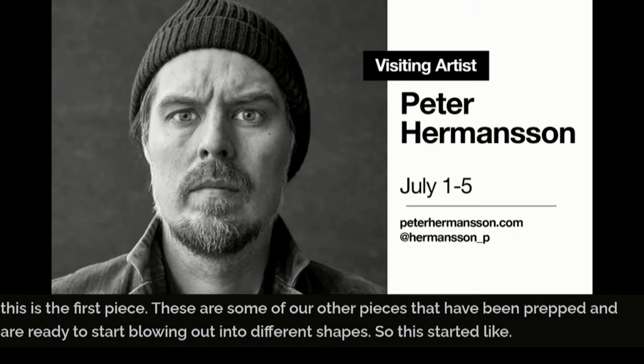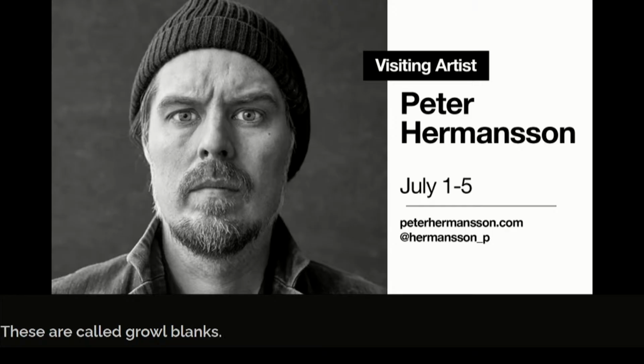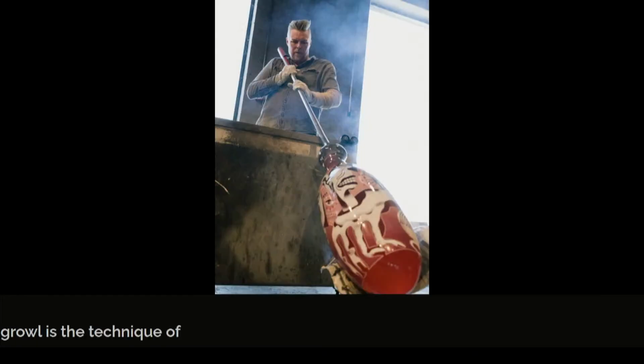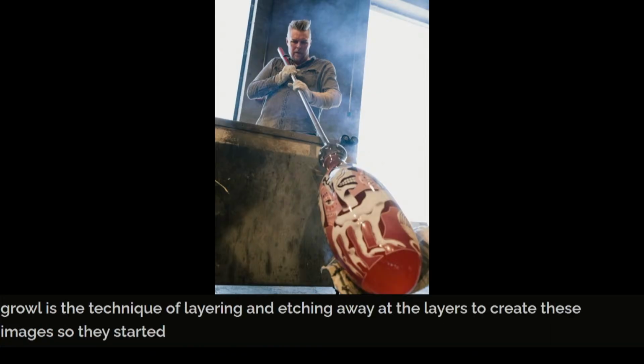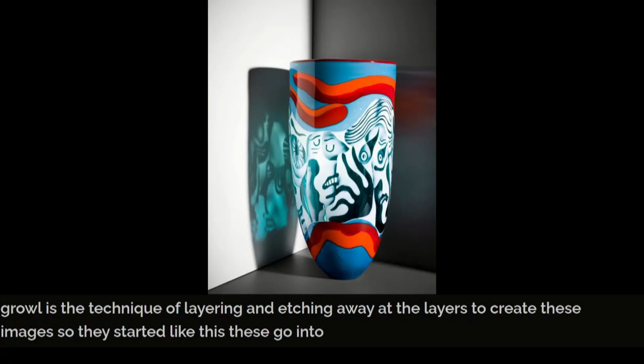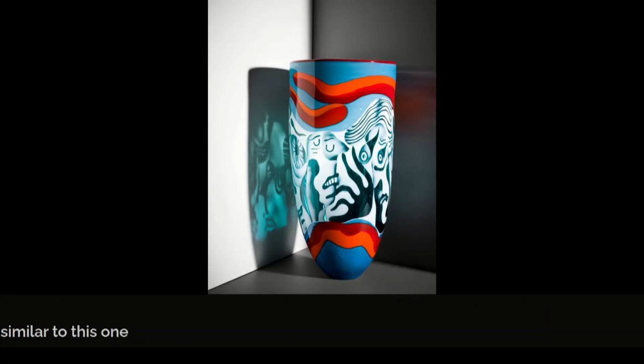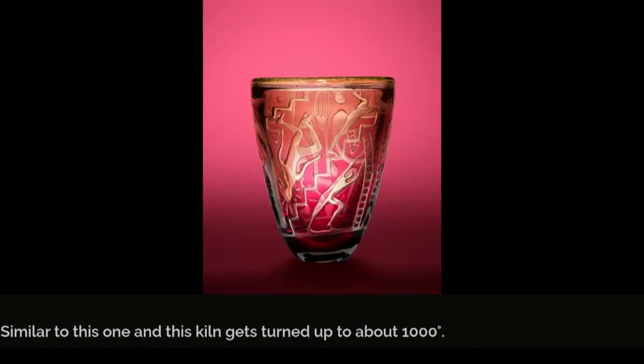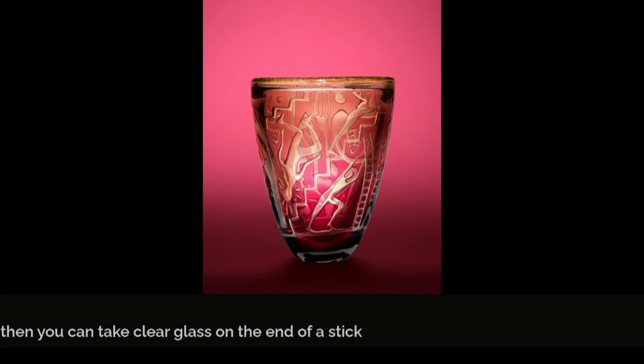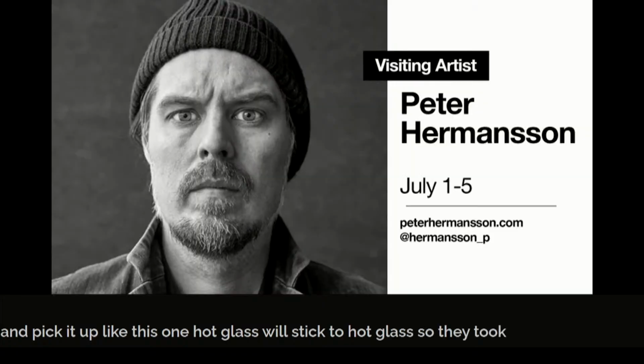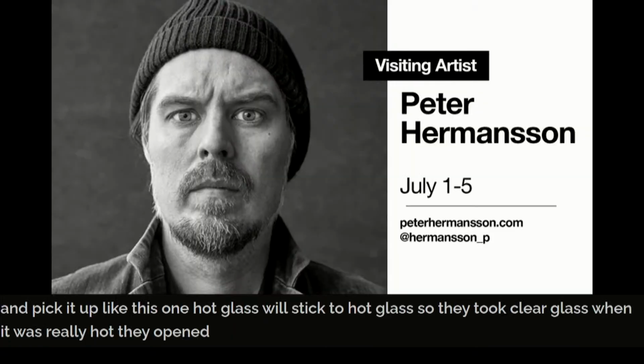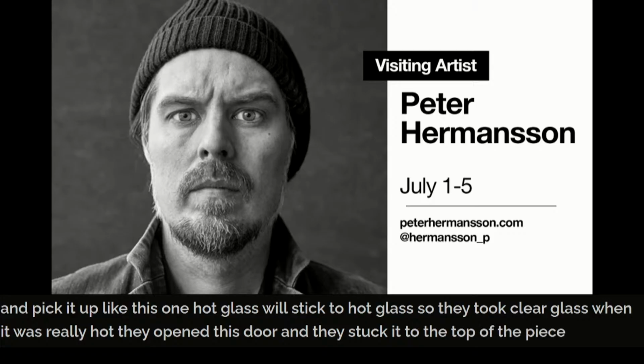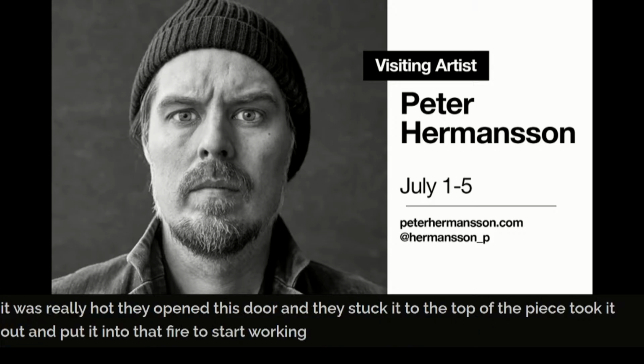These are called Graal blanks. Graal is the technique of layering and etching away at the layers to create these images. So they started like this. These go into a kiln similar to this one, and this kiln gets turned up to about 1,000 degrees. Then you can take clear glass on the end of a stick and pick it up like this one. Hot glass will stick to hot glass. So they took clear glass when it was really hot. They opened this door and they stuck it to the top of the piece, took it out and put it into that fire to start working on it.